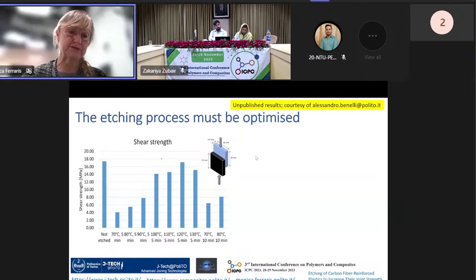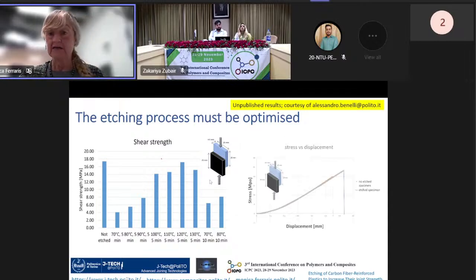For joint strength, we do lap shear in compression with these two samples, using a standard size and shape to compare results — this is not pure shear, just lap shear. The goal is to do better than the non-etched case. As you can see, if the etching is not perfect, you can get bad results, lower than expected. However, if the etching process is good enough, we start increasing the joining strength.